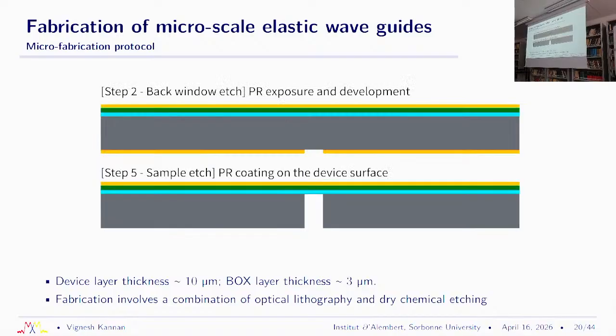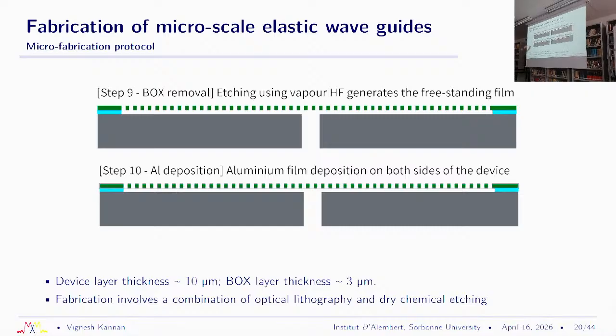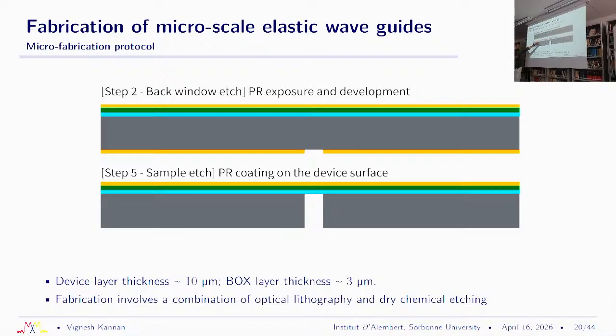So what we ended up doing is you put photoresist, which is basically a photosensitive polymer, on the top and the bottom. We etch a window into the bottom surface, so you can use etching techniques to essentially etch a window into the bottom surface, and I'll tell you why we need this window very soon. And then we create our architecture on the top surface, right? And here we are limited by the resolution of the photolithography system, right? When I say photolithography, I'm referring to the ability to create a pattern on this photosensitive polymer layer.